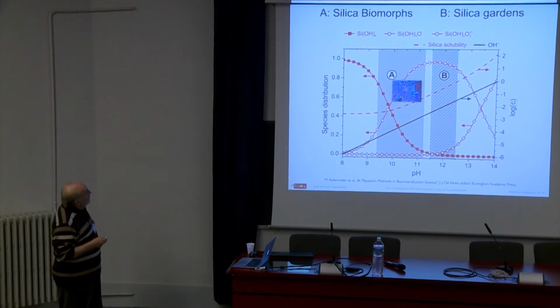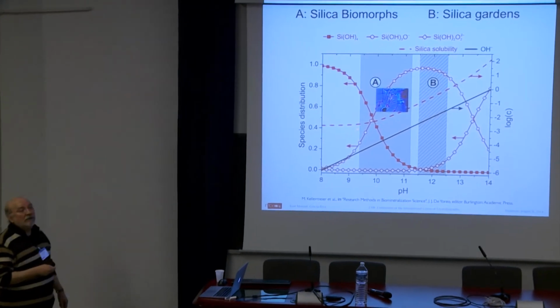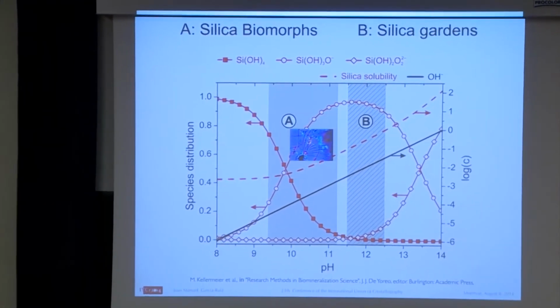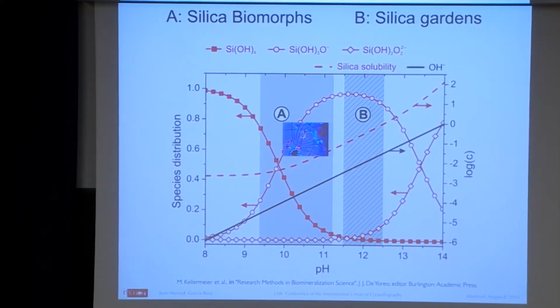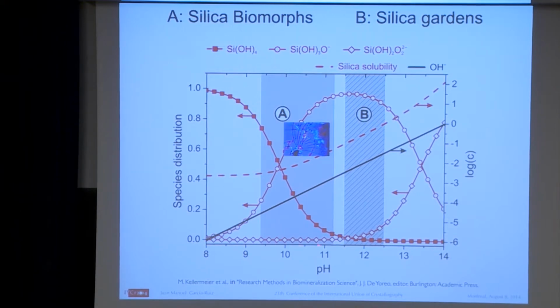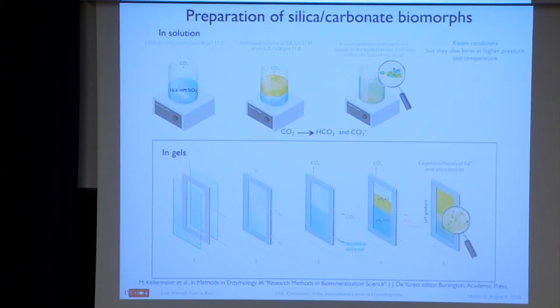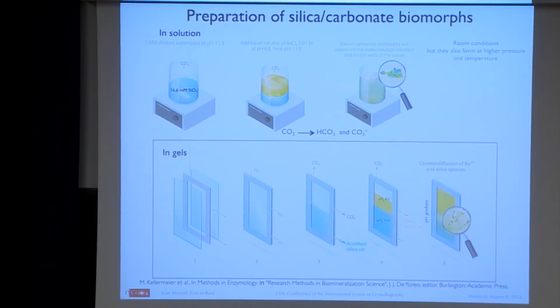So let me tell you before about what happens when you have a co-precipitation of carbonate, barium carbonate or calcium carbonate or strontium carbonate with silica rich solution, a pH between 9.5 and 11. Okay, you produce this experiment. This is very easy to do. This is an experiment where you take a solution rich in silica with pH 11.3, and then you allow the CO2, atmospheric CO2, to go into the solution. So when you add a solution of barium chloride, or calcium chloride, or strontium chloride, an alkaline earth metal, then the final pH is about 11, okay?